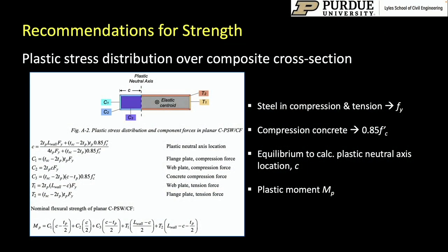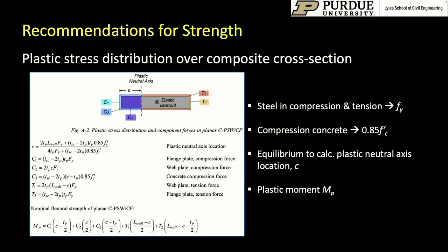In terms of calculating the in-plane flexural strength, we recommend the plastic stress distribution method over the composite cross-section. You're looking at it here. The steel in compression and in tension is assumed to develop Fy. This is only possible because in compression, we made the steel plates compact or non-slender by meeting the requirements that I talked about earlier. That's why it can form Fy in compression as well. The concrete in compression reaches about 0.85 f'c. You use equilibrium to calculate the plastic neutral axis and then the plastic moment capacity. Equations such as this are given for multiple different composite sections in the upcoming design guide.